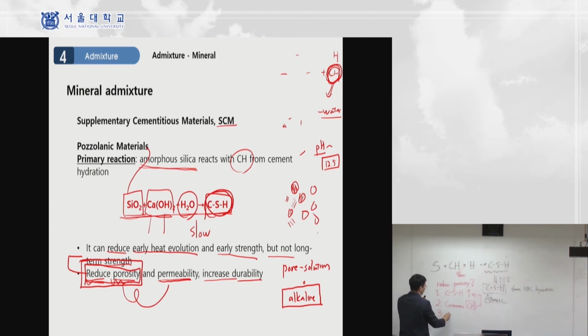And lastly, the time difference. Time, because this reaction is very slow, okay? So what that means is this pozzolanic reaction is very slow, but the effect of this pozzolanic reaction on material property is very high. It's very good, because when this pozzolanic reaction occurs, the cement hydration has already started, right? Because OPC hydration starts almost immediately at the beginning, but the pozzolanic reaction needs time because it does not begin at the beginning. It needs hydration product. Without this calcium hydroxide production from OPC hydration, this reaction will not occur, right?